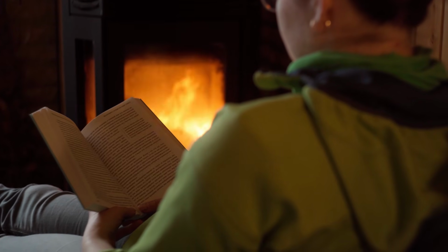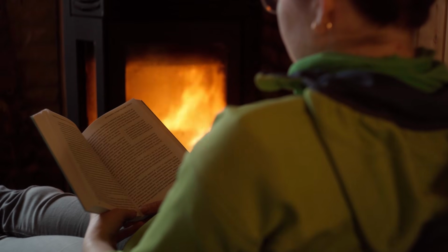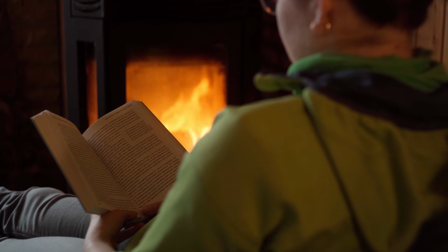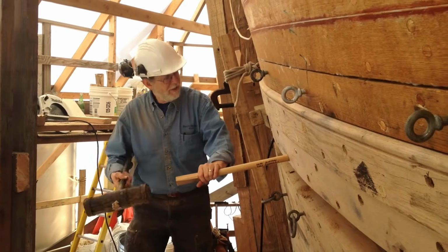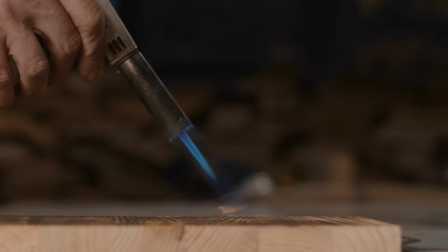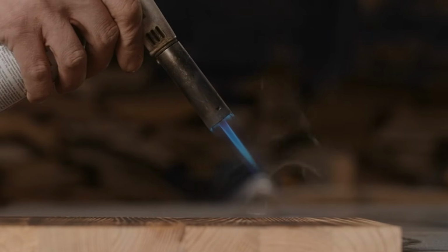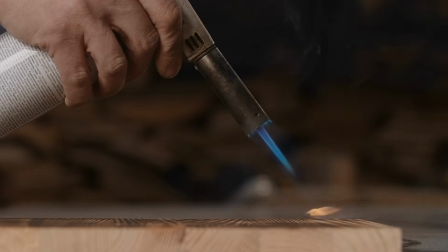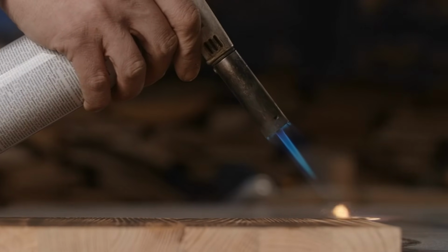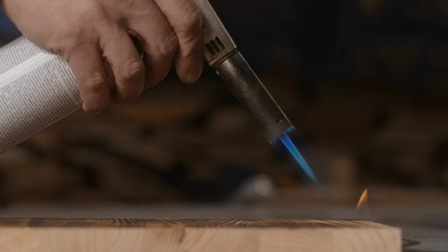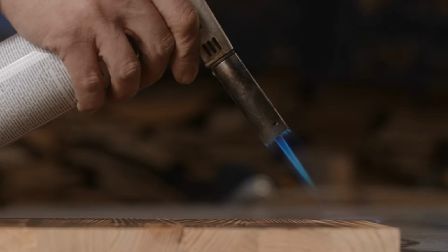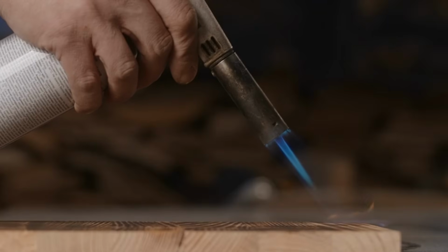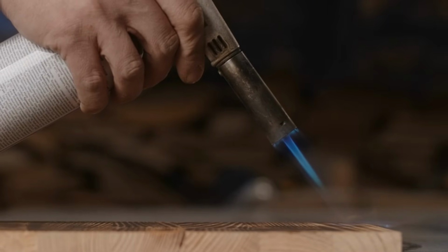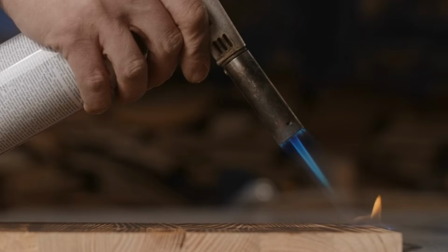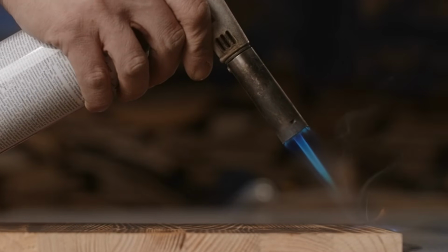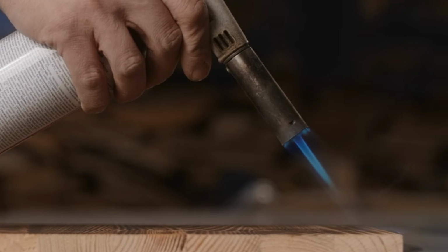This is something I came across studying old Royal Navy dockyard manuals, and I've never seen it mentioned in any modern woodworking resource. Before driving a tree nail, shipwrights would lightly char the ends over a small fire or with a heated iron. Not a deep burn, just enough to darken and harden the outer surface. The charring does two things. First, it hardens the end grain, so the tree nail seats more cleanly in the hole without mushrooming or splitting as you drive it. Second, the thin layer of carbon is naturally resistant to moisture penetration and fungal attack. It's essentially a microscopic coating of charcoal, right where the fastener is most vulnerable, at the end grain.